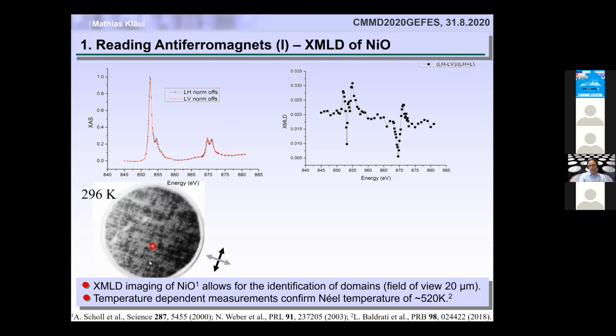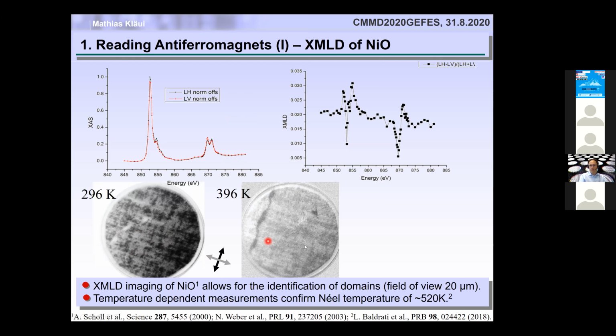You see here at 300 Kelvin, we see domains, and note that the bright-dark contrast is now not right-left or up-down, but it's 90 degrees different. Black means sublattices on Néel vector pointing up-down, and gray means sublattices on Néel vector pointing right-left. We can heat the sample, then the contrast goes down, and at the Néel temperature, the contrast completely vanishes. So there is some topographic contrast remaining, but that allows us to determine the Néel temperature of this system.